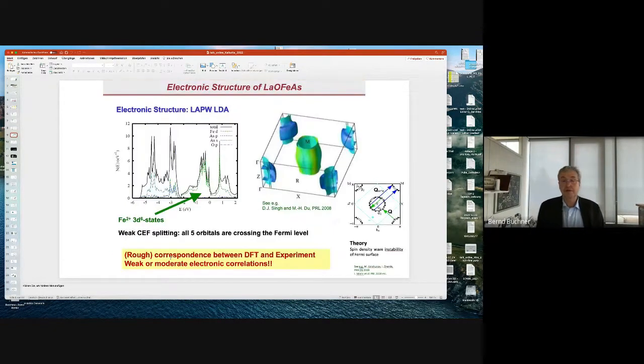And this is different in these iron-based superconductors. These systems, okay, again, as in cuprates, band structure predicts a metal. It predicts a metal where all relevant orbitals cross the Fermi energy. And this is also at least in rough correspondence to the experiment. So the parent compounds are metals or bad metals. I will come to this later on, but they have a complicated Fermi surface. And this is also taken from some very early papers where you have, let's say, at the gamma point, some pockets here, and at the M point, you have some pockets here. So complicated Fermi surface. And then if you have this Fermi surface, at least in the parent compounds, the pockets have similar size. So you have something like a nesting condition, and this stabilizes a spin density wave. And that's the way people discuss this antiferromagnetic state.